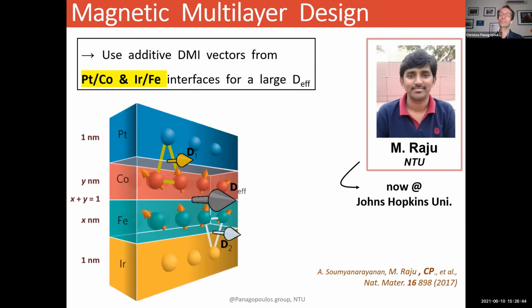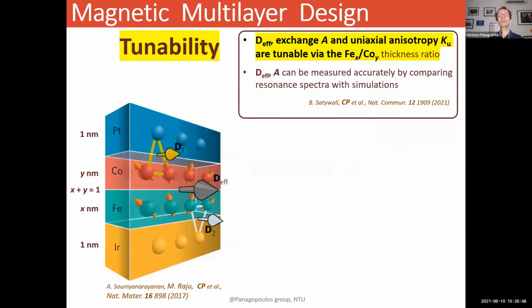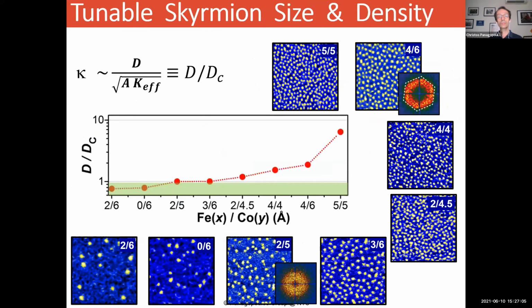change the effective Dzyaloshinskii-Moriya vector. And that allows you to have tunability. You can tune the effective Dzyaloshinskii-Moriya, you can tune the exchange anisotropy, uniaxial anisotropy, and all this by changing the thickness of your iron cobalt layers in your heterostructure. But also you can see here, by changing this thickness, then you can change not only the size of your skyrmions, but also the density.